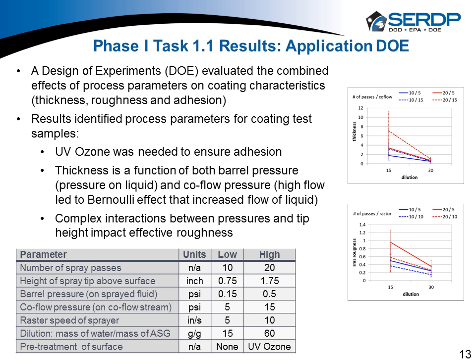So if we go to slide 13, one of the first things, of course, is taking the liquid glass, looking at these ASG materials, and making sure we run a design of experiments, stick to the science in terms of how we should spray it, what kind of pressures, what's the height of the nozzle off the board, what gives us the best spray parameters. And these graphs are a little bit of an eye chart, but you can always blow those up at your leisure. And you can see we're able to determine several things.